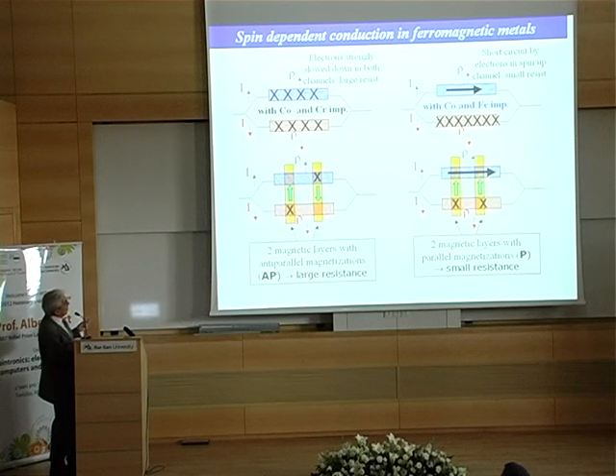This is more or less the concept of the GMR. In the GMR, we put on the way of the electron two magnetic layers. The situation where the magnetizations are in opposite directions corresponds to the cobalt-chromium situation — one layer stops electrons in one channel, the second layer stops electrons in the other channel, and resistivity is high. On the contrary, by applying a small magnetic field, you can align the magnetizations in the same direction — you are now in the cobalt-iron situation — and one of the channels is free. This is the concept of the GMR.